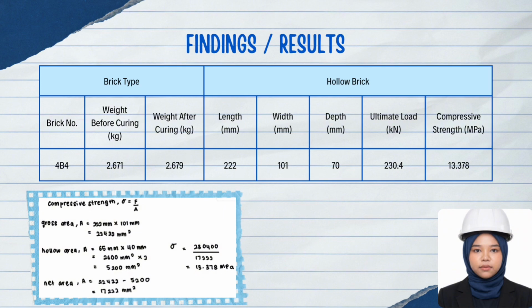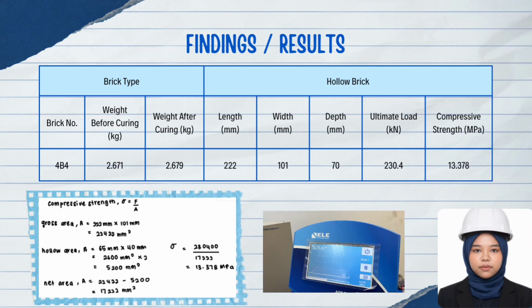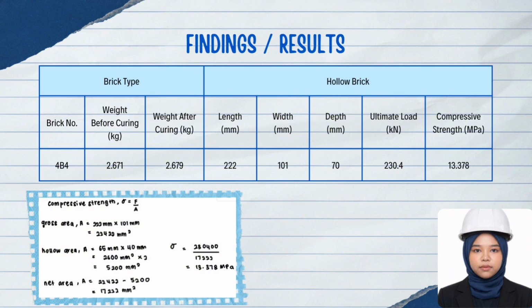The figure attached shows the calculation of compressive strength, which is done by subtracting the hollow area from the gross area to get the net area value. The brick reached an ultimate load of 230.4 kN during the compression test, resulting in 13.378 MPa of compressive strength. As a result, this indicates that the brick had good load-bearing capacity and is able to withstand a high compressive force before failure.